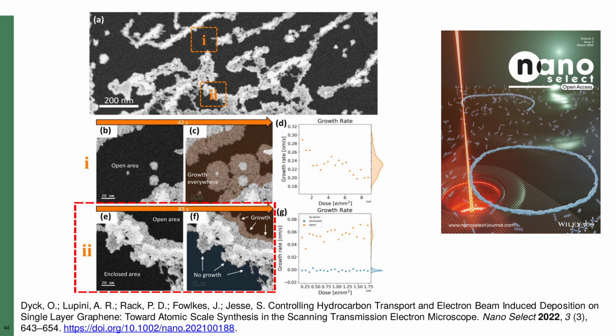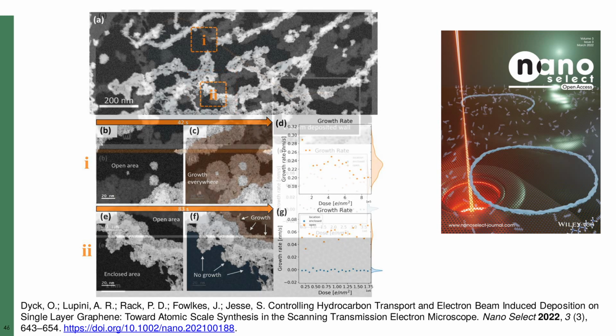What we notice is that growth only occurred on one side of this barrier. Looking back at the overview image, we can see that the difference is that one side of the barrier is a region that is completely enclosed by a continuous barrier that encircles the graphene, while the other side is connected to channels of clean graphene off to infinity.